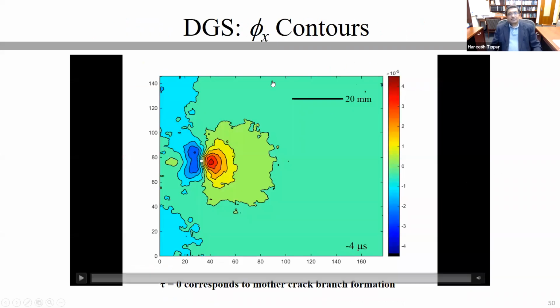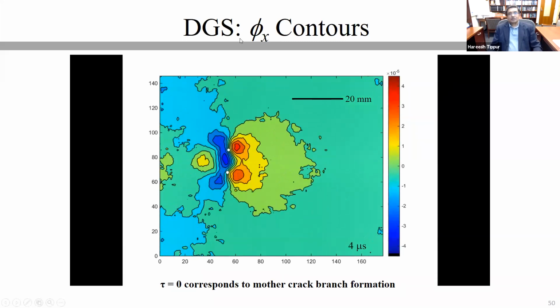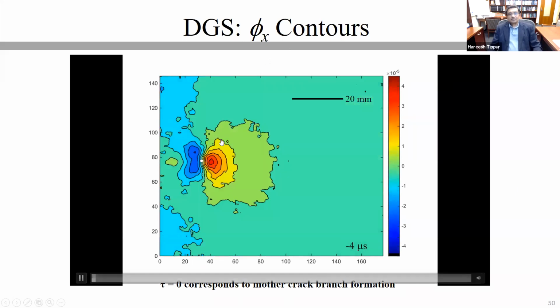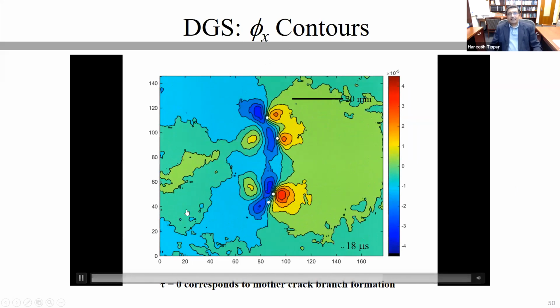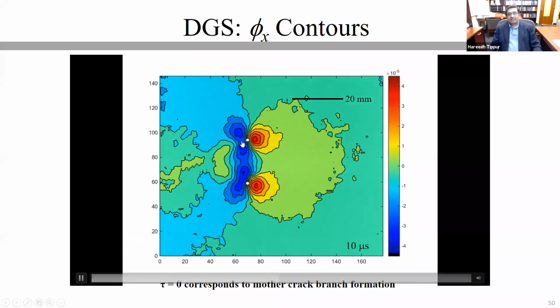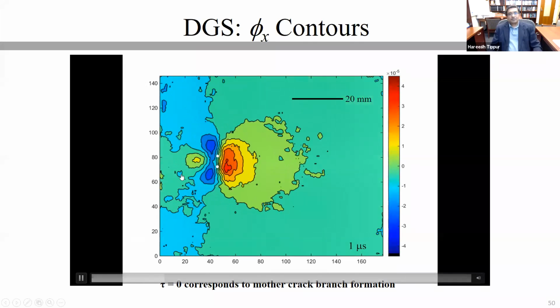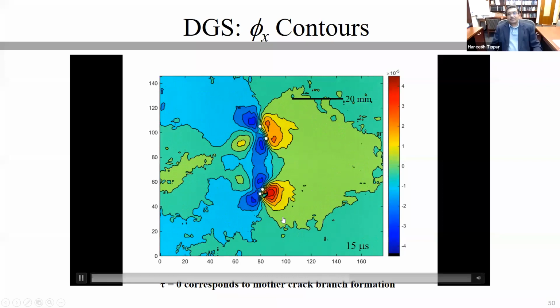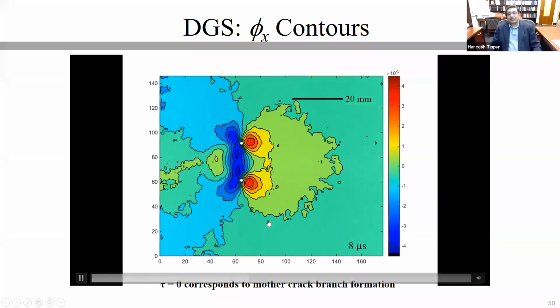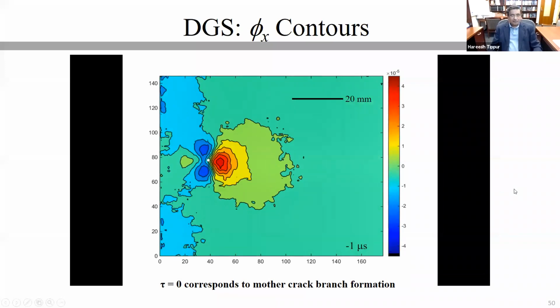Here is a little animation of our Phi-X contours. As I noted, you will see a little bit of mother crack growth, then it produces bifurcated daughter cracks, and then granddaughter cracks also. This is Phi-X contours. These contours are once again 2.5 microradian per contour. So you can see the dots represent your current crack tip position. The crack initially propagates and then branches. And then basically at the end of the event, you're seeing 4 different sets of these Phi-X contours propagating from 4 different crack tips, all occurring simultaneously.